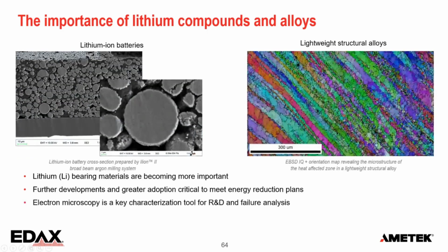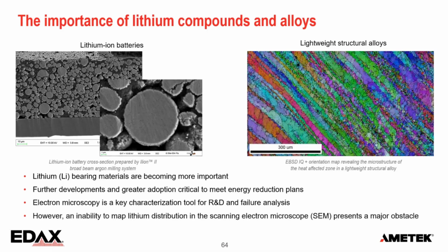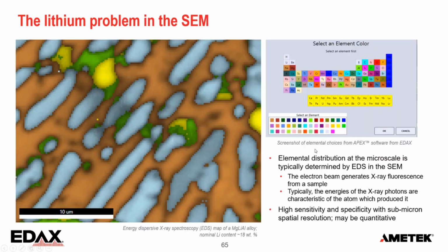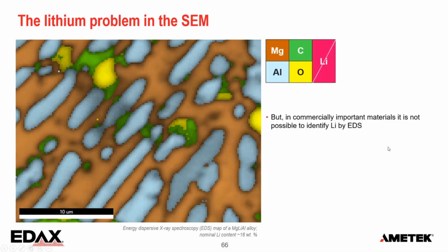And when we look here, we can get SEM images of these battery materials. We can do EBSD mapping of these structural alloys, but you cannot see lithium. So when you look at EDS mapping, then lithium is typically invisible. So what can we do there? Just as an example, this is a small map of a magnesium lithium aluminium alloy, which has 18 weight percent lithium in it. And we can identify the magnesium, aluminium, there's a bit of carbon in here as well. So we can see that, but we cannot see the lithium.